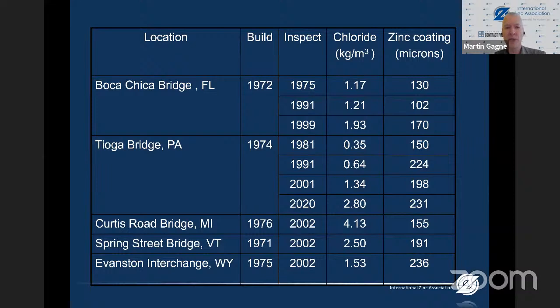The latest bridge that was sampled was the Tioga Bridge, built in 1974. We did a core sample last year, very high chloride loading, and still quite a lot of zinc left on the reinforcing steel. Now, the rebar coating thicknesses vary. Sometimes it's less, sometimes it's more. We can never sample in the exact same location. So this just reflects the variability of the product as it was delivered. But in all cases, we have a significant amount of zinc left on the rebar, and these bridges should go their 100-year design life with no corrosion on the rebar.